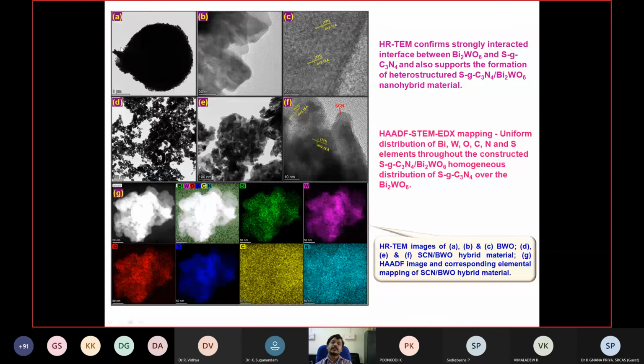Then the TEM analysis also clearly showed the heterojunction formed in that material. This belongs to bismuth tungstate, and this is sulfur-doped graphitic carbon nitride. Then the elemental mapping image shows the presence of all the elements in the hybrid material, especially bismuth, tungsten, oxygen, sulfur, carbon, and nitrogen. All the elements are homogeneously distributed in the material.